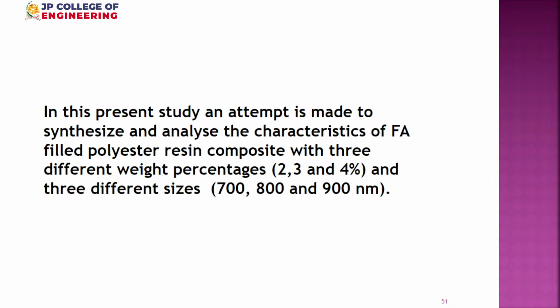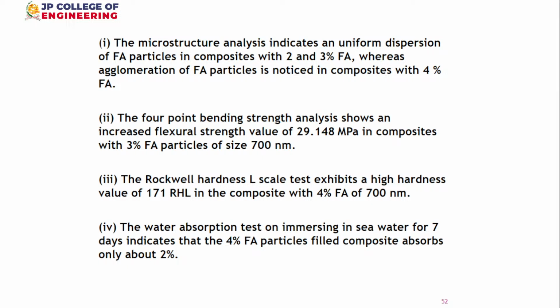Okay, so next slide. So this was the study. 2, 3, 4% fly ash with 700 nanometer composites have been prepared and studied. Next slide, please. Microstructure wise, 2% and 3% are better, 4% is not uniformly distributed. Flexural strength wise, 3% gives a high value. Hardness wise, 4% gives the better value. Water absorption wise, 4% absorbs more, so that is not suitable.